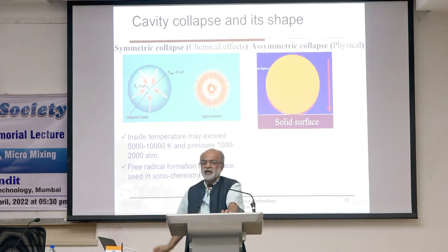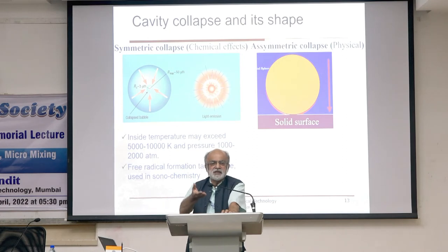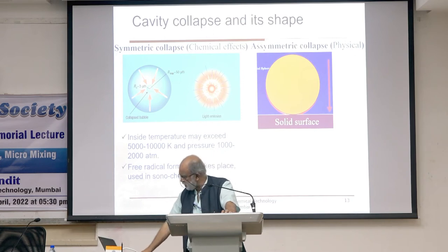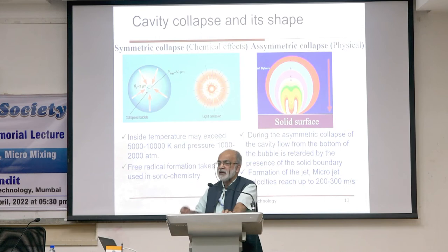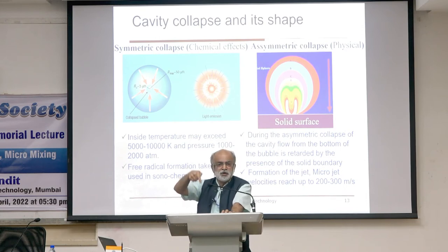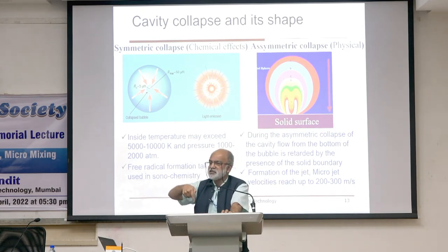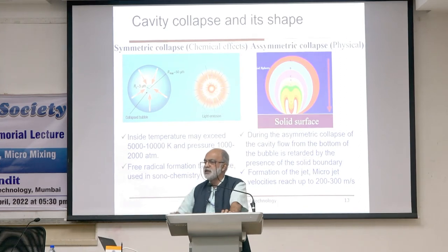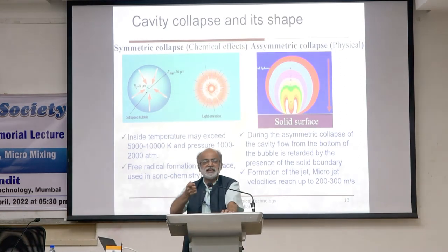However, if the cavity collapses on a surface, it does not collapse uniformly, because on the side of the surface there is no allowance for the liquid flow to come. So the cavity does not collapse symmetrically, but it collapses asymmetrically. Asymmetric collapse of the cavity generates a liquid jet pointed towards the surface, and this jet has a velocity of 200 to 300 meters per second. It is like a jet cutting.